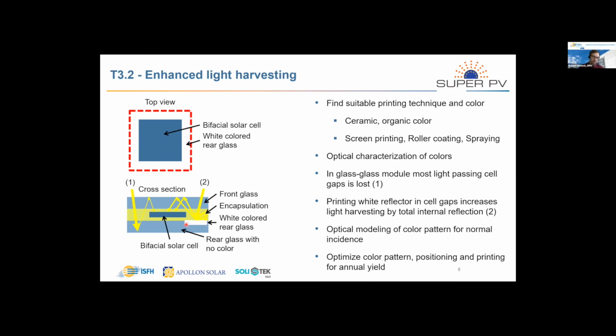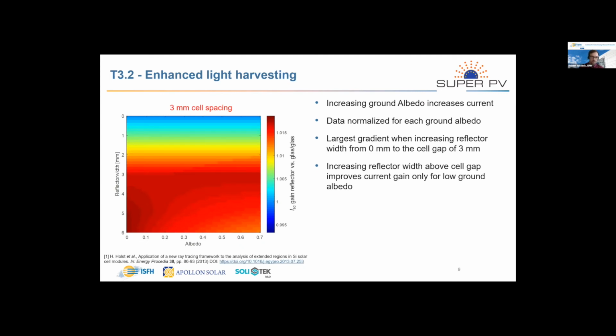And if you make it too large, you will shade the rear side of the cell, which is then detrimental if you have a ground albedo, where you still want to have the bifaciality of the PV modules, so that you can also collect light hitting the PV module from the rear side. So therefore, we used a ray tracing approach, and some results are shown here for a module with a cell gap of 3 millimeters. And this two-dimensional graph here shows the ray tracing simulation results.